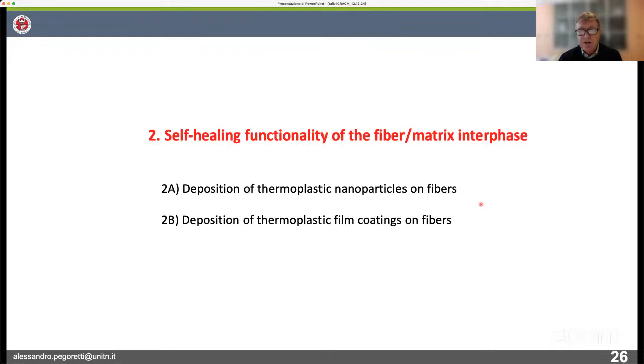So in order to reach this, we have to use several techniques. The one we decided to use is to deposit a thermoplastic material in form either of nanoparticles or a continuous film coating on the surface of the fiber. At this point, if there is a layer of a thermoplastic material on the surface of the fiber, we can imagine to apply a temperature increase in order to melt the thermoplastic polymer and to somehow restore the initial adhesion.